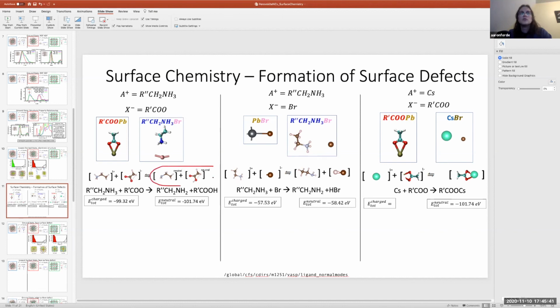And this one I do observe in the molecular dynamics. When the charged version of this carboxylate leaves the surface, it steals a proton from ammonium nearby, and then this acetate just freely floats in the simulation box. So in some sense, it is a surface proton transfer reaction.